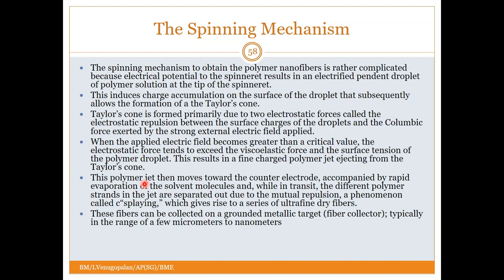When the applied electrical field becomes greater than a critical value, the electrostatic force tends to exceed the viscoelastic force and the surface tension of the polymer droplet. This results in a fine polymer jet ejecting from the Taylor's cone. This electric field has to exceed a critical value, and that critical value is based on the type of polymer that you use. The polymer jet then moves towards the counter electrode, which is accompanied by rapid evaporation of the solvent molecules. Because you don't want the solvent in there. You just want the polymer.